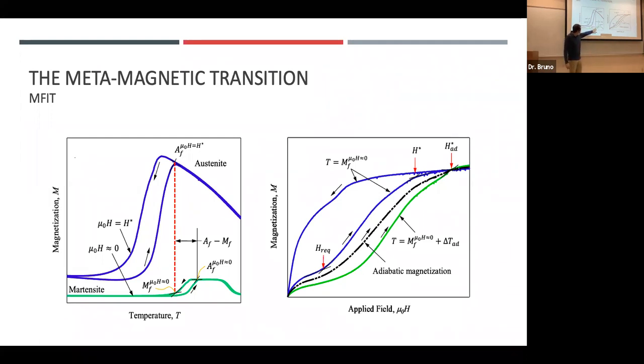But if we start originally at the martensite finish temperature, we heat our material to that temperature, and then hold temperature constant and ramp magnetic field, eventually our field will be large enough so we'll be in the austenite phase. And you can envision it, or do kind of a thought experiment, you decrease these transformation temperatures at a certain rate as you apply the field. If we looked at the simultaneous magnetization versus applied field curve, we're going to magnetize martensite to this H required, is what I call it. Essentially, that's like shifting this green curve to a point where this initial bend reaches our MF temperature. We're going to push it into the austenite phase until H star. H star means the austenite finish temperature now equals what MF was.